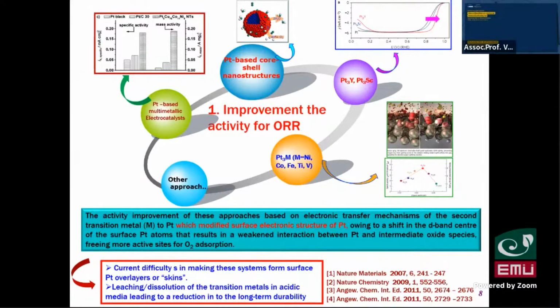The second thing is that the second metal, when making alloys with platinum, can also cause problems like leaching into the solution. During fuel cell operation in acidic media, this leads to a reduction in long-term durability.